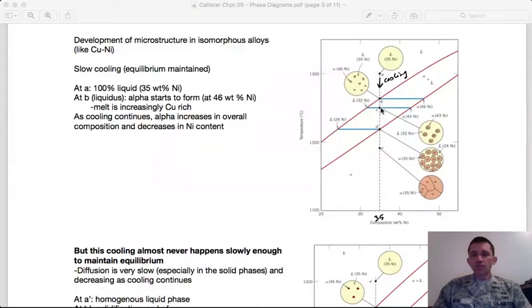And then as we cool down further and further, we are solidifying more alpha around the outside of these grains. I can draw my tie line across, and I see that the composition of alpha phase, as I grow my grains outward, sort of like the tree rings on a tree, I have rings, and each successive ring has less and less nickel in it, as I move down through this region. And so at this point C, I'm at 43% nickel, and the nickel content of my liquid continues to drop. As I get down to the bottom here, I'm almost completely solidified. And so the outside layer here is...